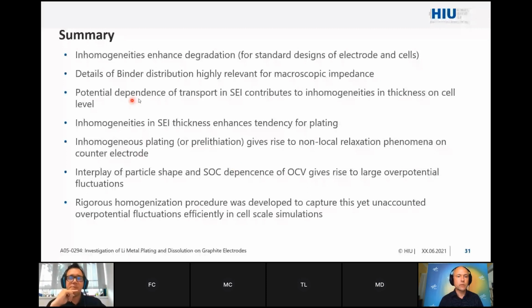I pointed out that the specific transport mechanism, which leads to the strong potential dependence, will lead to inhomogeneities in the thickness of the SEI on cell level. The inhomogeneities again enhance the tendency for plating. Inhomogeneous plating again gives rise to non-local relaxation phenomena on the counter-electrode, for example. So suddenly you do something on the anode and you influence the whole inner environment of the battery.